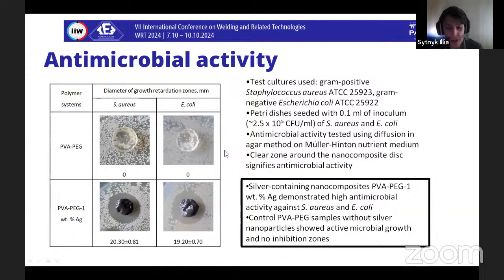The cups were incubated from 24 hours to 48 hours at a temperature of 37 degrees Celsius. The indicator of antimicrobial activity was the presence of a clear zone around a nanocomposite disc. The larger the zone around the disc, the higher the inhibitory efficiency. A nanocomposite disc without silver nanoparticles served as a control. Experiments were repeated 3 times. The interpretation of the results was carried out according to the diameter of the growth retardation zones of microorganisms around the discs, according to CLSI recommendations.